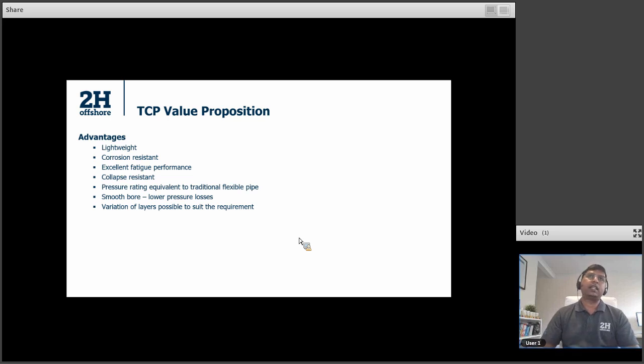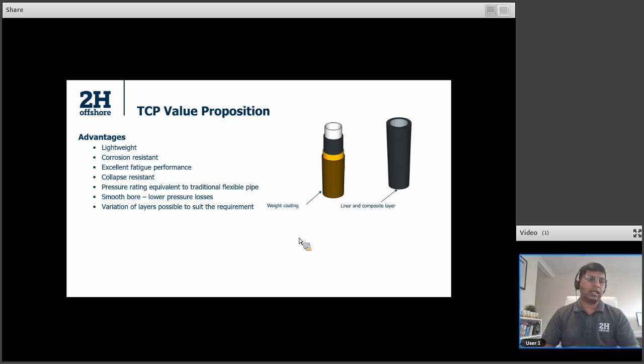I mentioned that the traditional TCP is lightweight, but if you want to make it heavy, there's a possibility to use a weight coating layer on top of your protective layer to give the required strength. But if you're using a very high resistant material such as PEEK, you can get away with just using a liner and a composite material, which also provides equally strong properties and high resistance against wear.